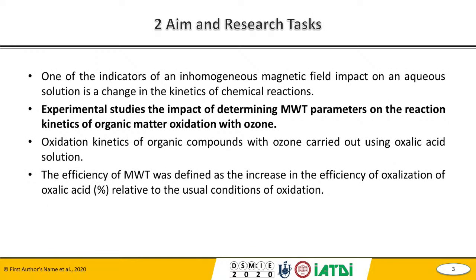One of the indicators of an inhomogeneous magnetic field's impact on an aqueous solution is a change in the kinetics of chemical reactions. So the main aim of this research is experimental study of the impact of determining magnetic water treatment parameters on the reaction kinetics of organic matter oxidation with ozone. Experimental studies were carried out using oxalic acid solution. It is relatively slowly oxidized by ozone, which made it possible to monitor the effectiveness of magnetic water treatment. The efficiency of MWT was defined as the increase in the efficiency of oxidation of oxalic acid relative to the usual condition of oxidation.